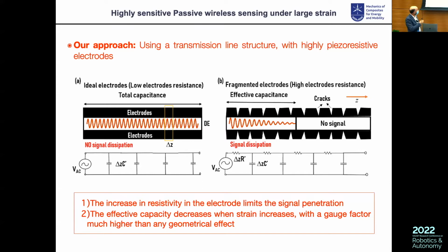Because if you do this, at low strain, let's say you have an electrode that is almost perfectly conductive. That means your interrogation signal is going to penetrate the sensor. But then as soon as you apply some strain to this, and I will show you in 1 minute that this piezo-resistivity is coming from cracks, the resistance of these electrodes is going to increase a lot. And due to the increase in resistance, you will limit the penetration of your interrogation signal, and the effective length of the capacitance is going to decrease and will be a function of the frequency, but mainly will be a function of the strain. That means when you increase the strain on these sensors, you reduce the effective size of your capacitance. And this is a way for us to have a change in capacitance that is much higher than the classical geometrical effect that you see in capacitive sensors, right?